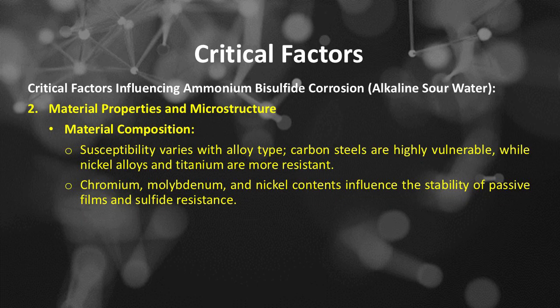Critical factors influencing ammonium bisulfide corrosion or alkaline sour water. Number 2 is material properties and microstructure, which includes, first, material composition. Susceptibility varies with alloy type. Carbon steels are highly vulnerable, while nickel alloys and titanium are more resistant. Chromium, molybdenum, and nickel contents influence the stability of passive films and sulfide resistance.